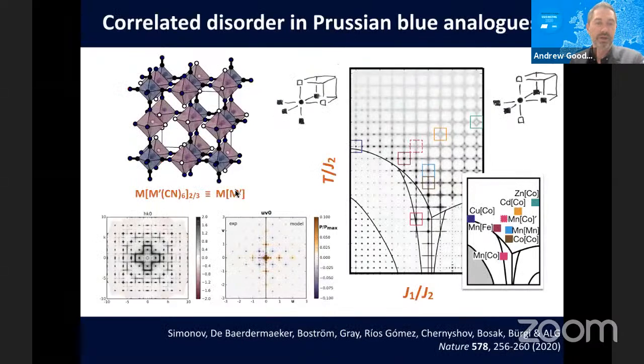In our own group, we've been looking, for example, at these Prussian blue analogues. This is a problem of vacancy correlations. These materials are used in all sorts of areas. Very often, one of the key features is the nature of the pore networks that run through them. And here we're using these diffuse scattering patterns and their three-dimensional difference pair distribution functions to infer information about the arrangement of these vacancies relative to one another.